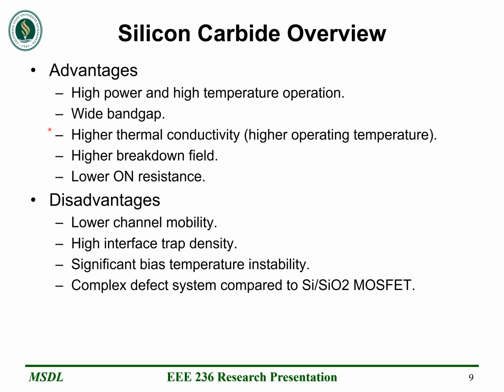So to summarize, some of the advantages of silicon carbide are the high power and high operating temperature, the wider band gap, higher thermal conductivity, higher breakdown field, and low on resistance, as we discussed. But as we saw in the previous table, some of the disadvantages like lower channel mobility can hinder performance in some applications. Additional disadvantages that we'll discuss in the coming slides are high interface trap density. Silicon carbide also can have significant bias temperature instability, and as we saw in some of the stacking sequences, this can present a complex defect system compared to regular silicon and silicon dioxides inside of a MOS transistor.